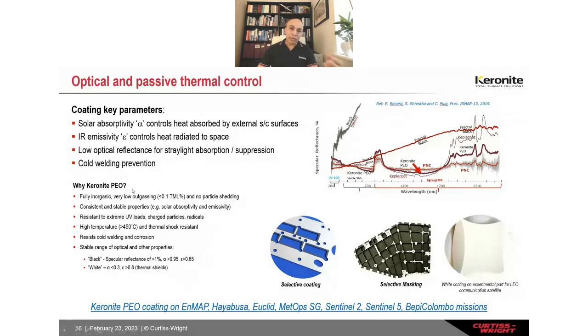So why Keronite then? Because, A, it is fully inorganic. It has very, very low outgassing compared to paint-based systems, right? It has very consistent and stable properties. In fact, several PEO coatings have been tested on the International Space Station's Columbus platform over 18 months with absolutely no change in alpha epsilon values from the beginning of life to the end of life.